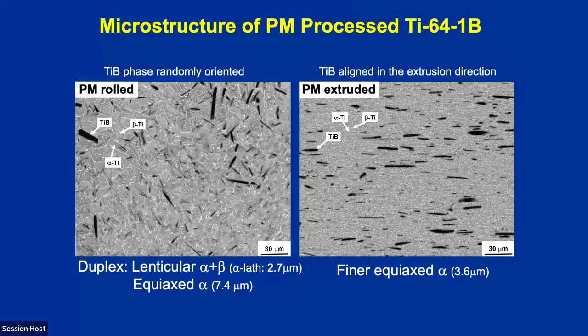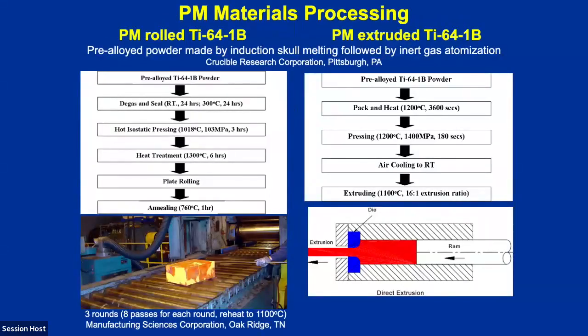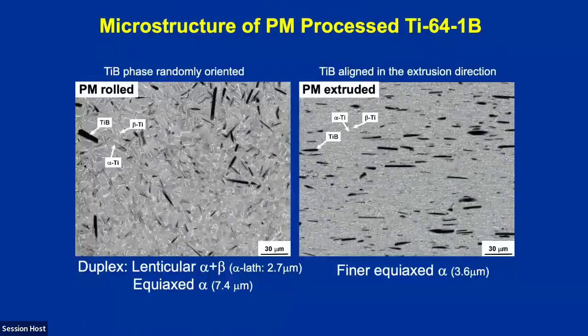And we found out that, for the same magnification, you can see a much finer alpha grain size, on the order of 3.6 microns, and it's double or higher in the rolled condition. And if we look back, the temperatures were relatively consistent between the two, up to 1200 degrees C for the processing. So that may have an effect on the grain size, but for sure we get this significantly happening, whether we have 0.1 boron or 1 boron, we get whiskers that are aligned with the extrusion direction.